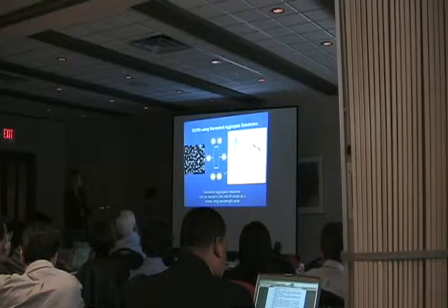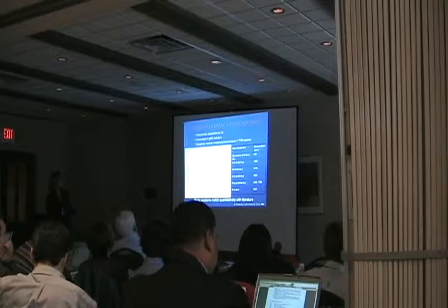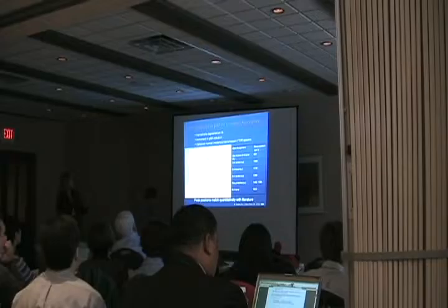And if we have a Raman active molecule, the same molecule we used for SERS, coating our nanoshells, we find that we get some beautiful surface enhanced infrared. This is actually the first spectrum we ever got, and we were kind of stunned because it was a whole spectrum of this molecule, surface enhanced infrared compared to the bulk. All of the resonances are there. Of course, the resonances that we see through SEIRA have this characteristic, very strongly asymmetric line shape, which has been previously studied theoretically quite extensively, actually. So we can see that it all scales very nicely.